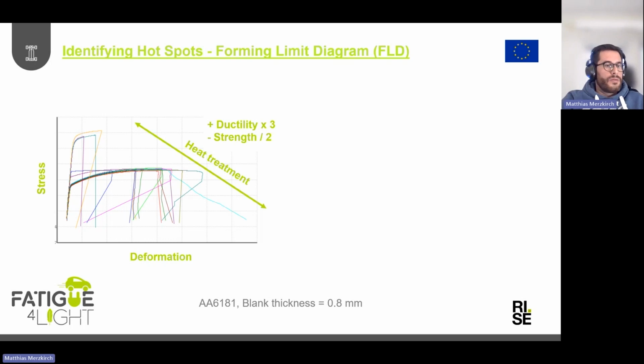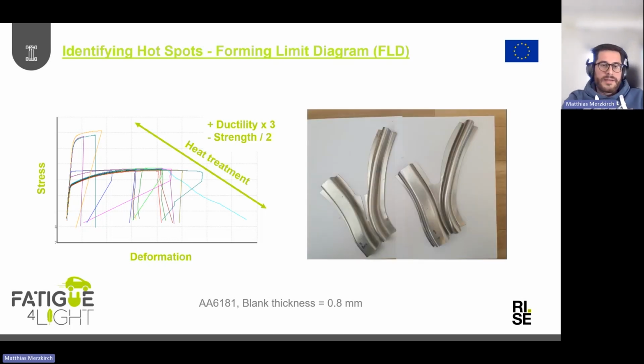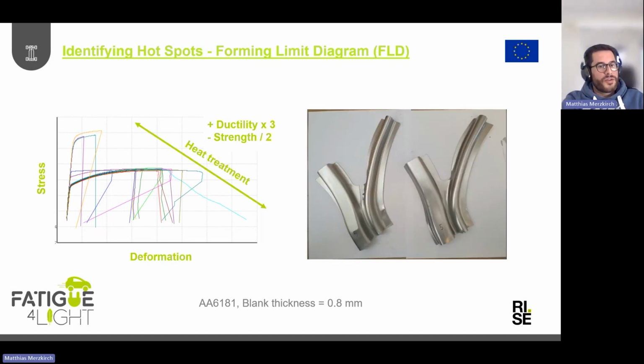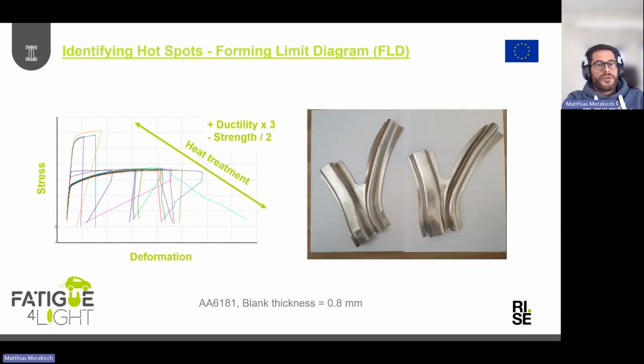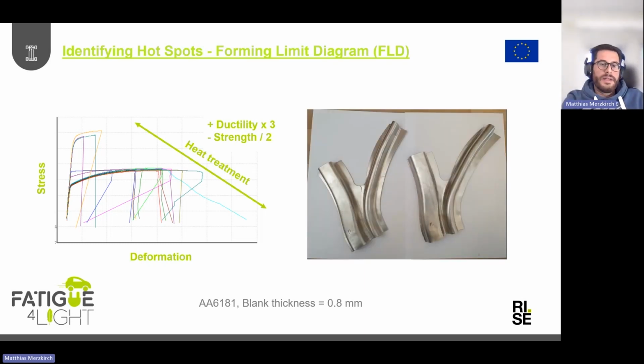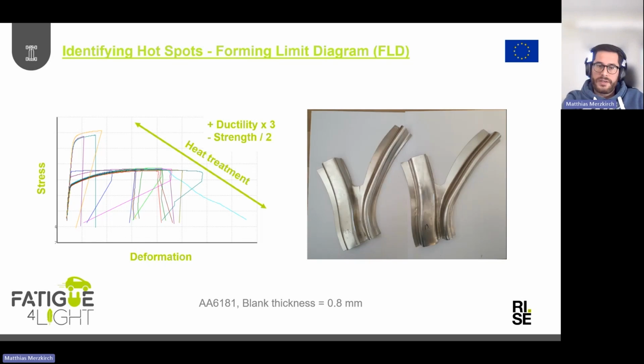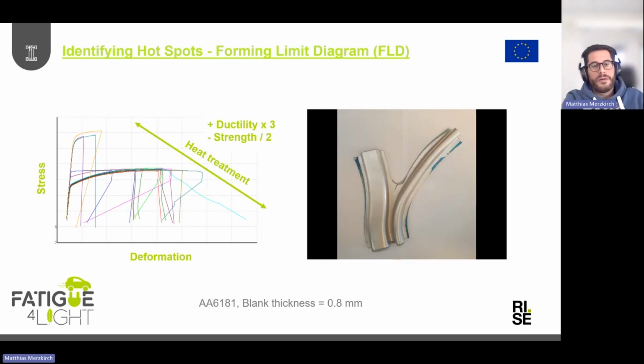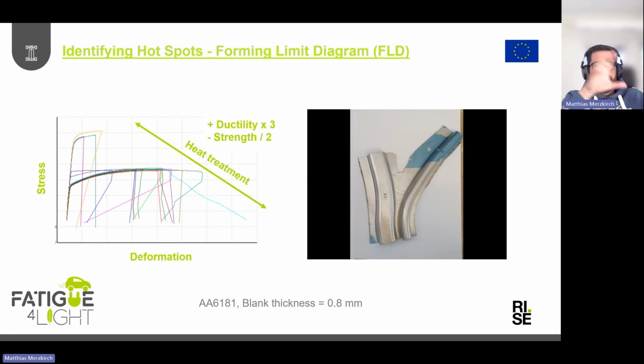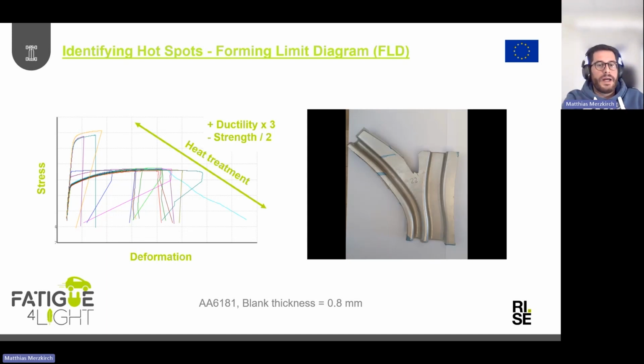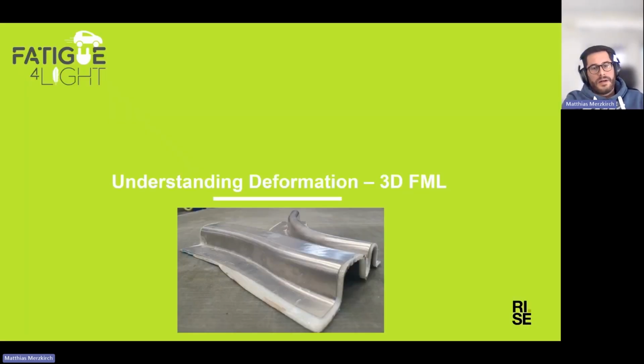But in that case, it was also possible to actually manufacture that and also to control the crack size and the cracking itself. So here, besides that heat treatment state, there were also different shapes. So how should this raw blank look like? Does it have a radius? What is the radius size? What is the overlap in the material, and so on? So many different procedures or different geometries have been tried out in order to find an appropriate one, and then also to do the manufacturing and to come to this three-dimensional fiber metal laminate.